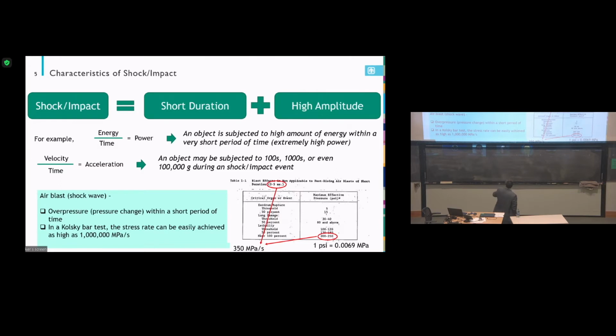Another example is air blast or shock wave. From this table you can see the duration of an air blast is generally about 3 to 5 milliseconds. Very short. And you can see how our body can handle it. Only 5 PSI over 3 to 5 milliseconds gives you an eardrum rupture. But if you apply 200 to 250 PSI over these 3 to 5 milliseconds, you 100% die. If you calculate this, that's about 350 megapascal per second. That's the stress rate, or pressure rate, that people can handle.